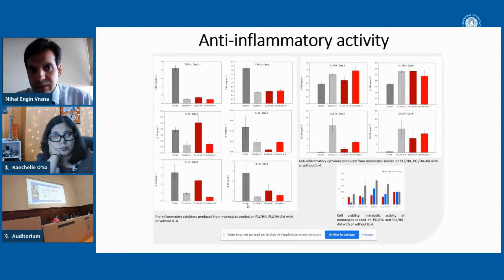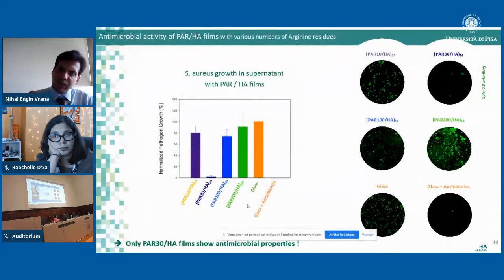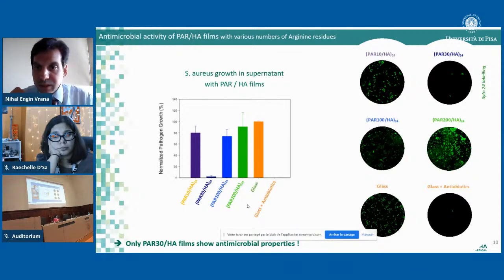But we started to notice that the nature of the coating has an effect by itself. If you look at the TNF-alpha levels or interleukin-1 beta levels, just having a self-cross-linking system with HA aldehyde has an effect. Having IL-4 accentuates this effect, but there's an effect by itself. And while we were looking at different configurations, we came across one configuration which has the same anti-inflammatory effect, but at the same time, at a very narrow molecular range, it also has an antimicrobial effect.